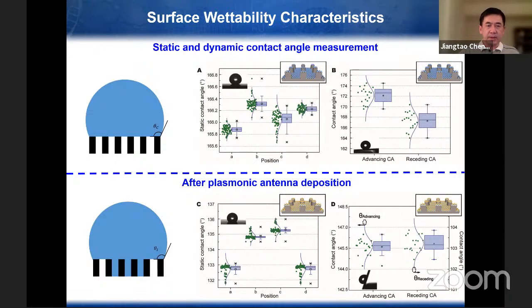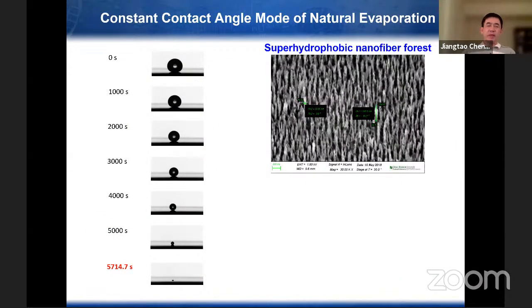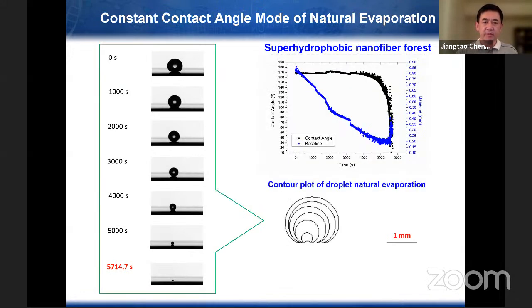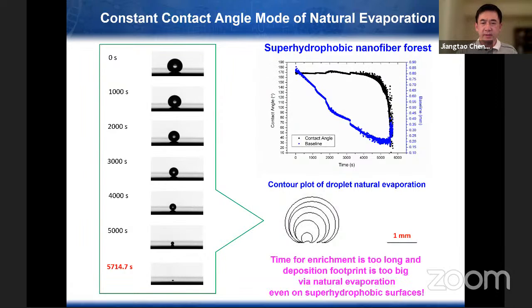And by controlling the droplet states on the nano antenna surfaces, we can control the evaporation enrichment of the content analytes. By natural evaporation, we can see the final footprint is on the order of millimeters. And also it takes hours to have the full evaporation of even the 4 microliter droplets. So this is too long, okay?